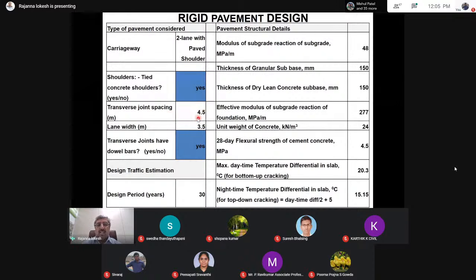Generally, the transverse spacing of 4.5 to 3.5 meters. Transverse joint, whether we are providing a dowel bar or not, design life of 30. Modulus of subgrade reaction, as I discussed, we can input the data. Thickness of granular subbase. Granular subbase will also act as a drainage layer in case of concrete pavement. Trial concrete thickness of 150 mm. Considering this as 150 mm, we can find out what is the effective subgrade reaction.